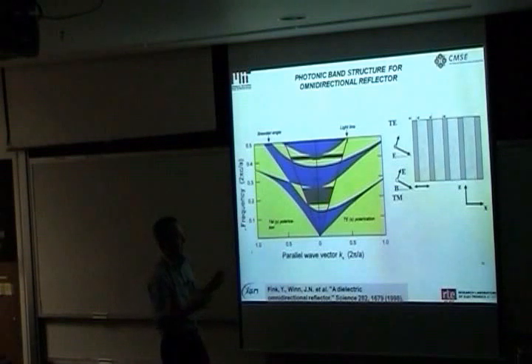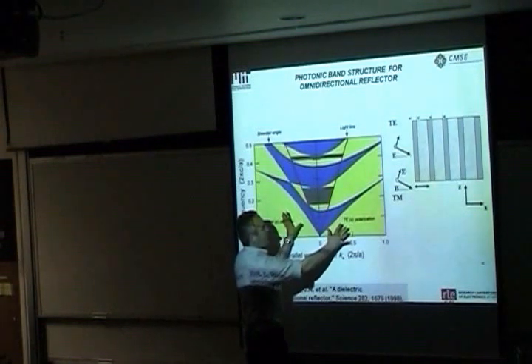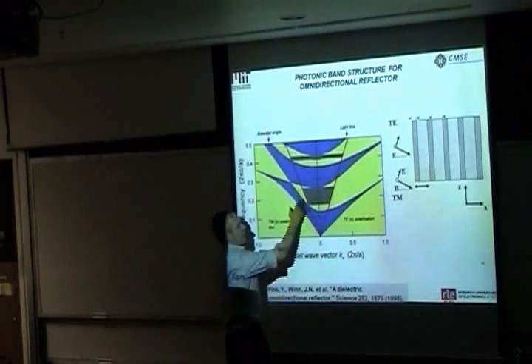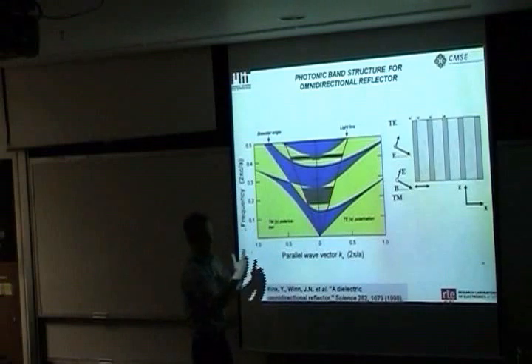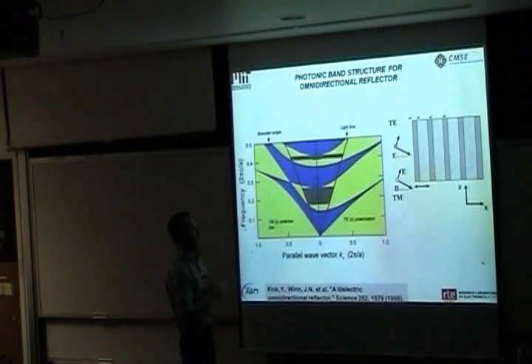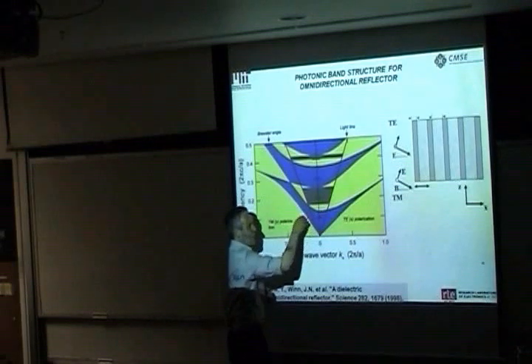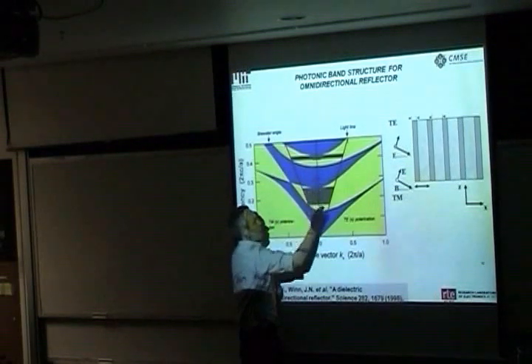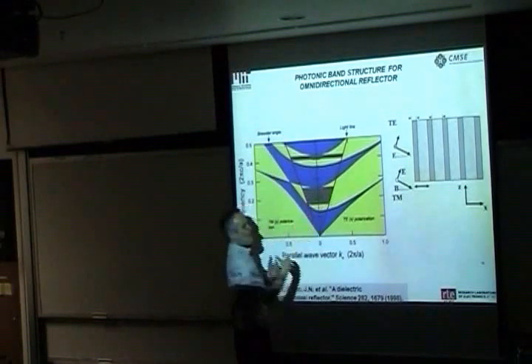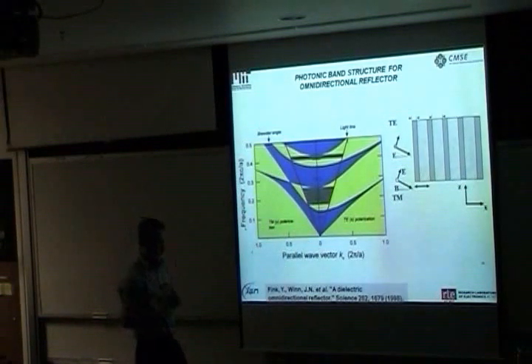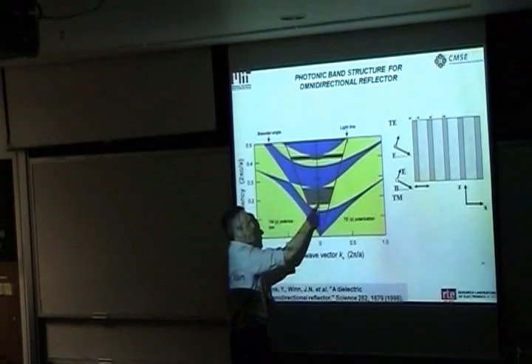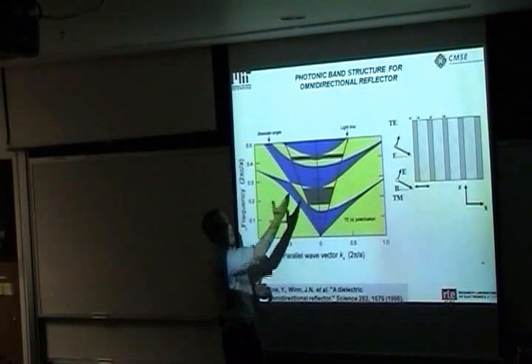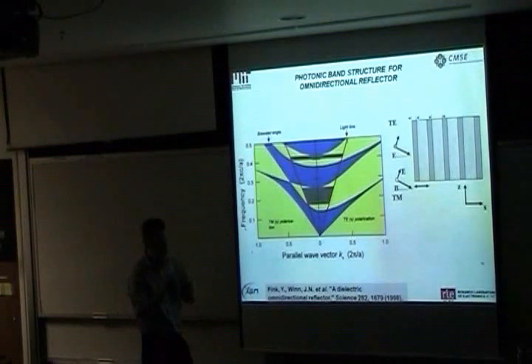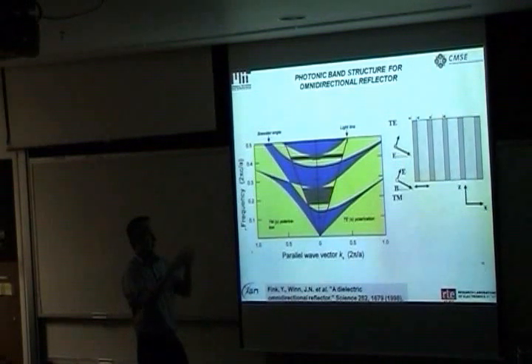translational symmetry. And basically, one could differentiate between a TE polarization and a TM. And what you see here are the solutions in blue, are propagating solutions of the infinite crystal, if we were to create one. These solutions actually are propagating in the crystal, and between the two propagating bands there actually is a range of frequency for which there's no propagating solutions. However, what you could always and immediately realize is that regardless of any frequency you choose, at some k vector, you always couple to a propagating solution. And this was the reason why, at least at the time, people thought that this type of structure could not reflect omnidirectionally.